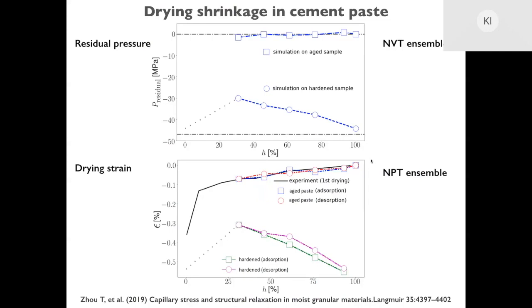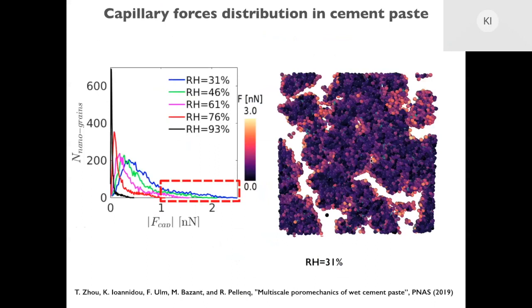Then with the simulations, we can of course go and understand where exactly we have the larger capillary forces in the material. So we have a resolution down to the cement nanograins, so down to a few nanometers. And here we can basically color code each particle with the capillary force it is feeling due to the water. So you don't see the water here, but you see from the color code that the bright particles are the ones that have the larger capillary forces.